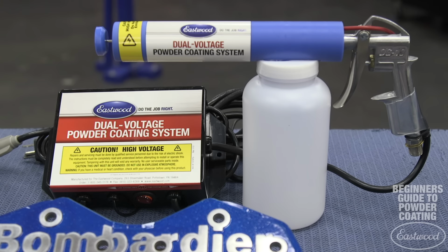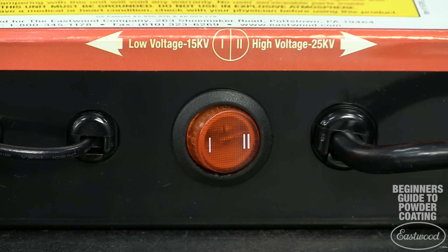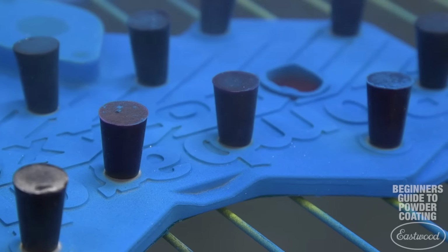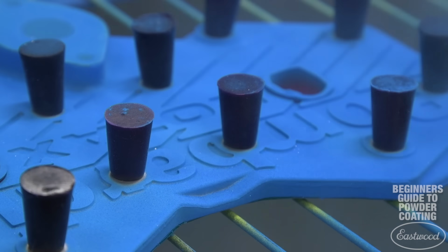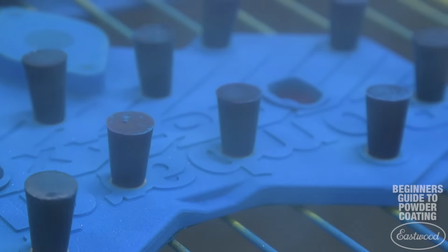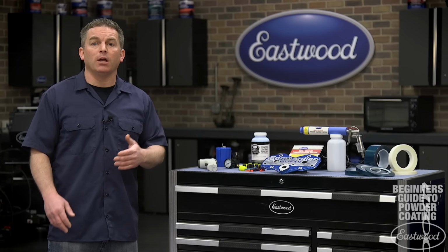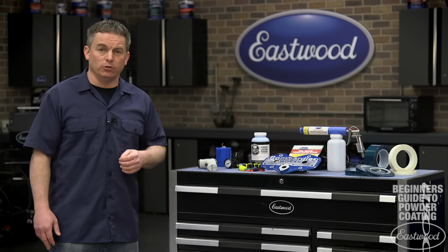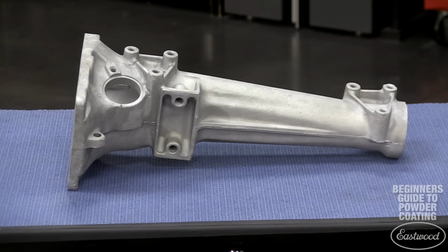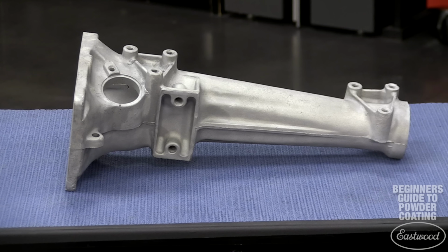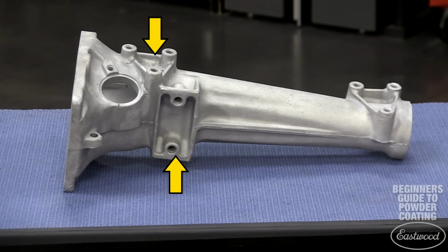A dual voltage gun like this one from Eastwood is great because you can switch the voltage to get the best coverage on large flat areas as well as in tight corners where you can get poor coverage due to the Faraday cage effect, meaning the powder will be repelled from those areas unless you're using a gun that allows you to adjust the voltage. Faraday cage effect happens most often in areas where the angles are about 90 degrees or tighter.